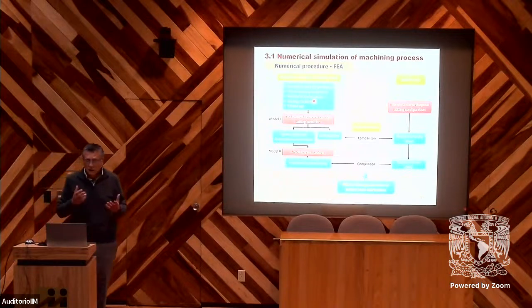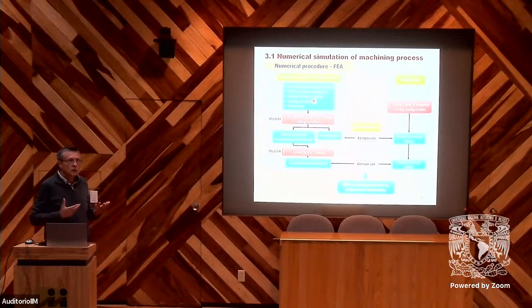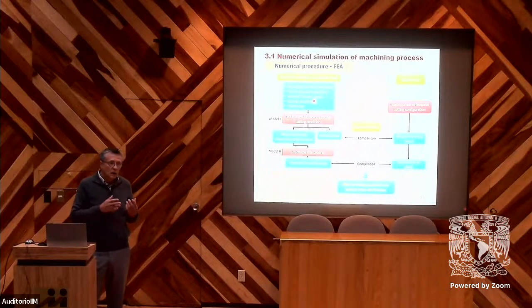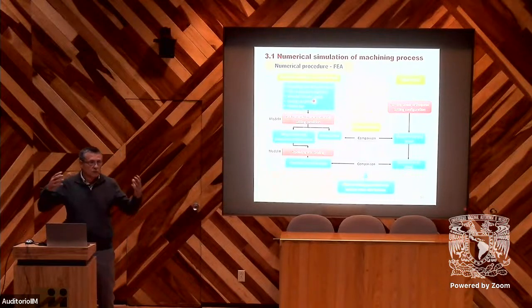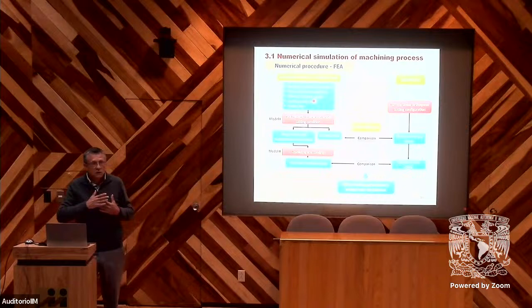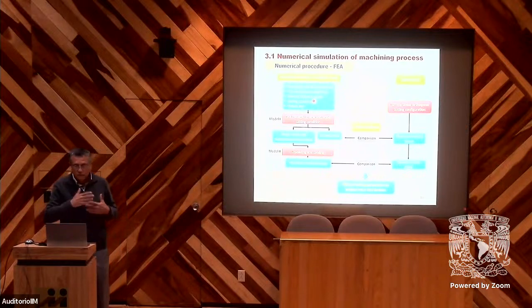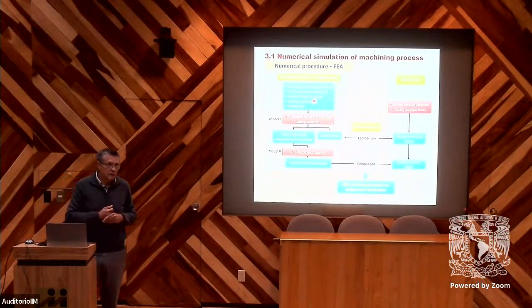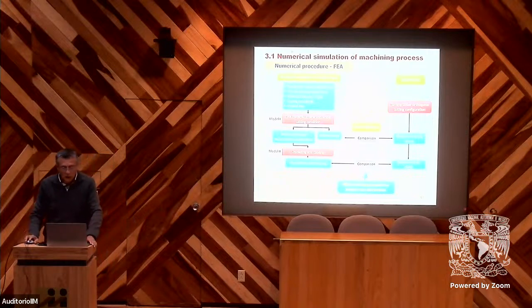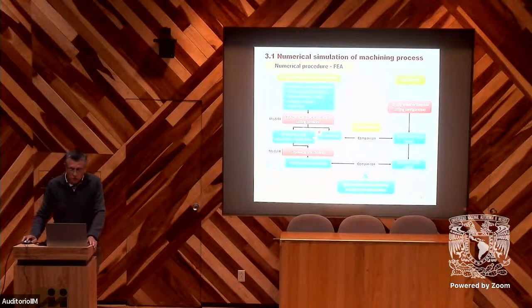of this. And this is very difficult because you need the behavior at different ranges of deformation and also at different ranges of strain rate. And then we can calculate the repartition of stresses, strain, and temperature, and so on, and also determine the cutting forces. And after unloading, this is the second model, we can get residual stresses.